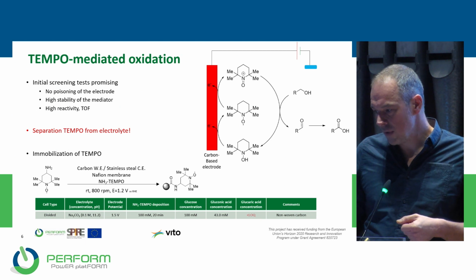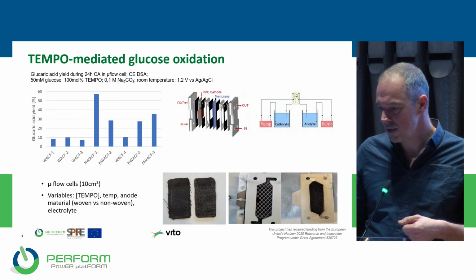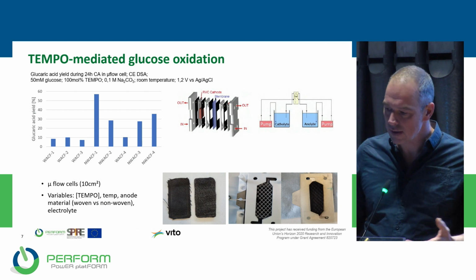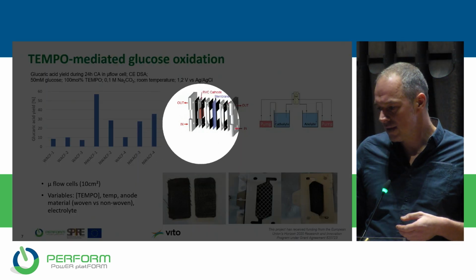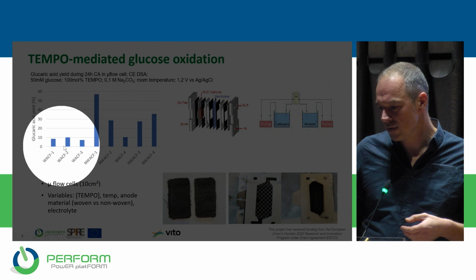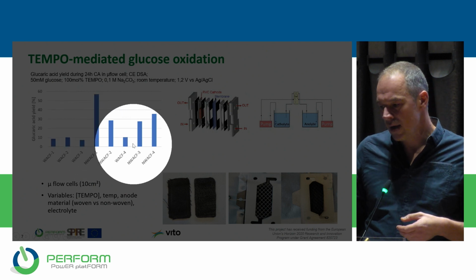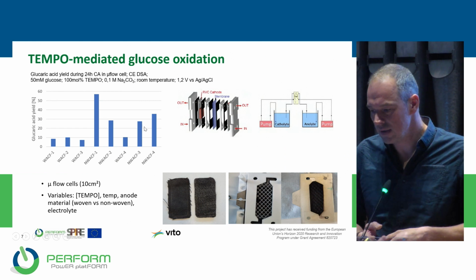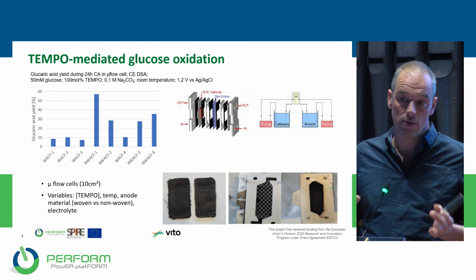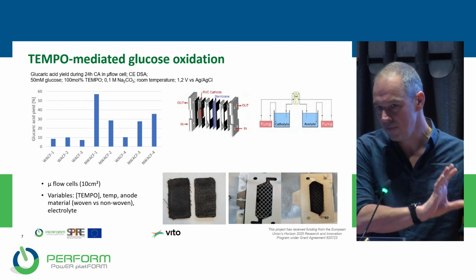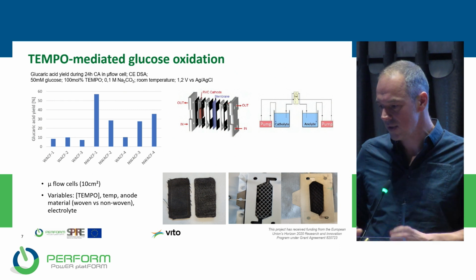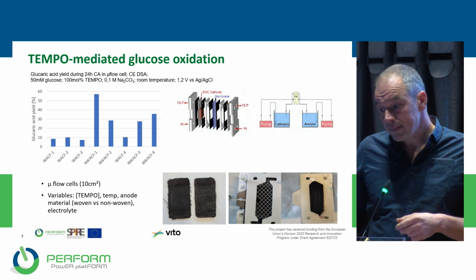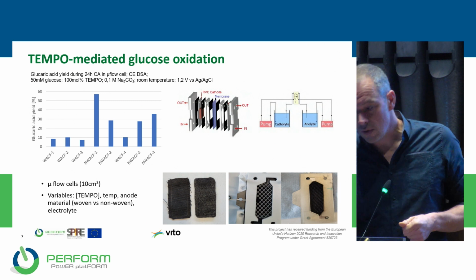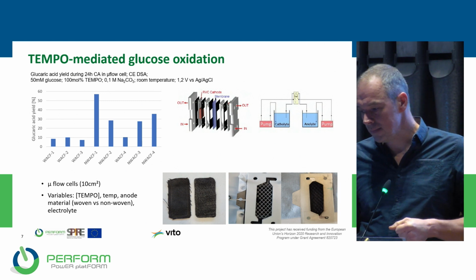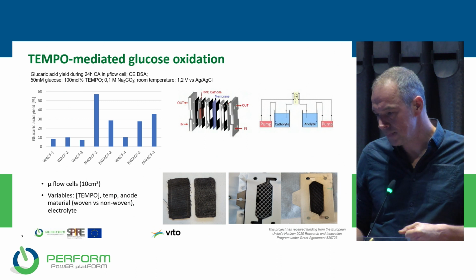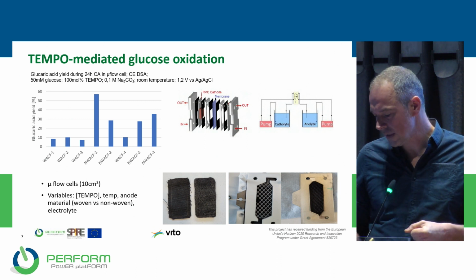So then we shifted back to a mediated oxidation. In flow cells, we really tried to figure out what is the best type of electrode that we can use in combination with the TEMPO and the glucose. We found out that in a micro flow cell, which is only 10 square centimeter, so we moved from a few square millimeters in H cells to 10 square centimeter, a non-woven activated carbon fiber was one of the best electrodes to be used in combination with the TEMPO.